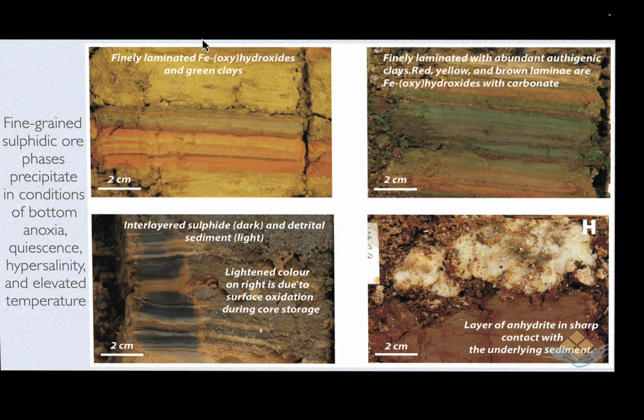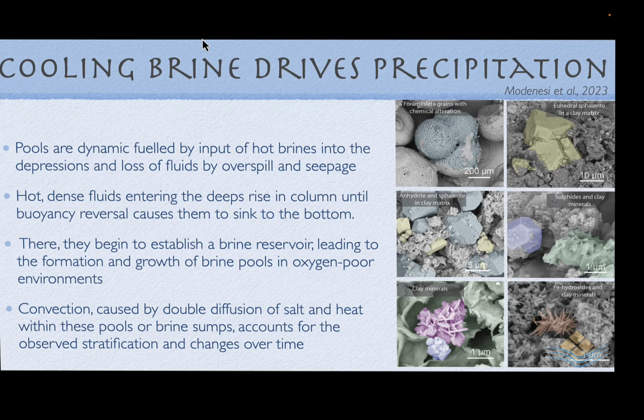These are hydrothermal anhydrites. These are forming by the cooling of 200 degree plus centigrade brines on the brine pool, and we're precipitating nodular anhydrite in contact with, in this case, an underlying laminated sediment. In these systems, all of the sedimentology indicates accumulation and settling, and then subsequent diagenesis in conditions of bottom anoxia, quiescence, hypersalinity, and quite elevated bottom temperatures. It's the cooling of the brine that's driving the precipitation of these phases.